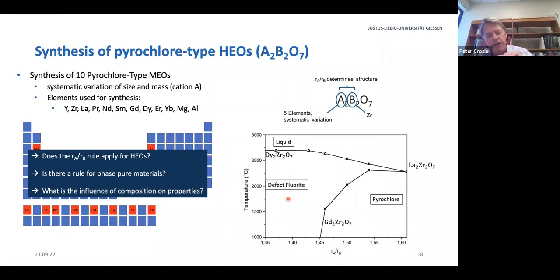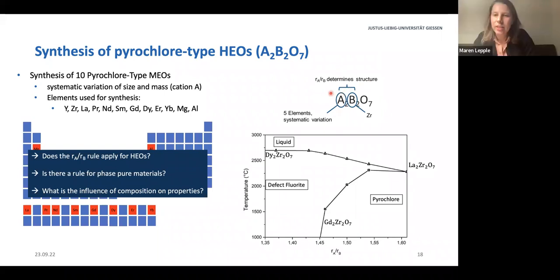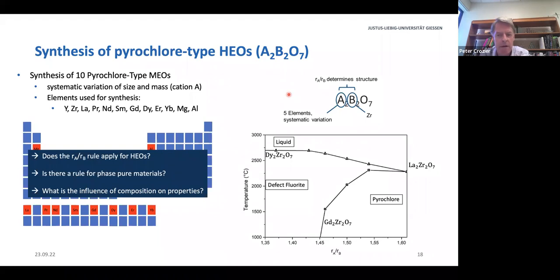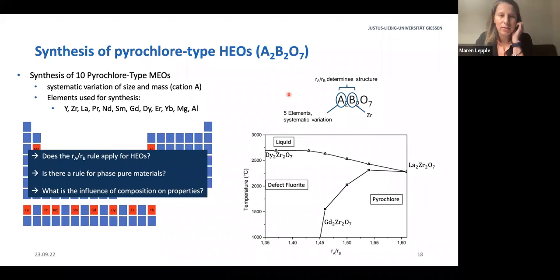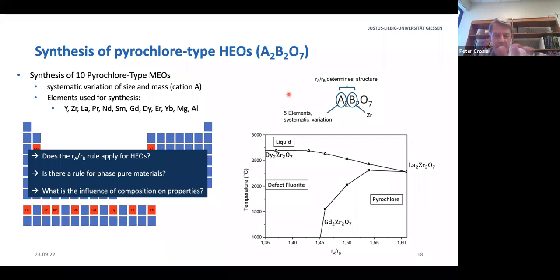But you start from pyrochlore and you exchange the A, is that correct? Yeah, we exchanged the A, but we kept it constant at 7. This is a trivalent cation, and we also used trivalent cations. For samples 9 and 10, we tried to add a divalent and a tetravalent cation, but this did not work. For example, we used magnesia and zirconia, and then we formed some magnesium oxide. So in the high entropy oxides, or in this class, there's always a kind of oxygen vacancy relative to the fluorite structure, is that right? It's always O7 when you make them? Yeah. I see. Okay, thanks. Interesting.